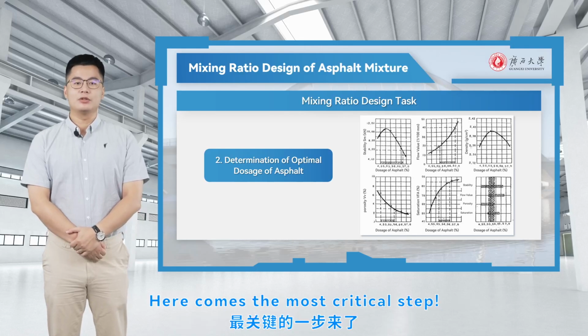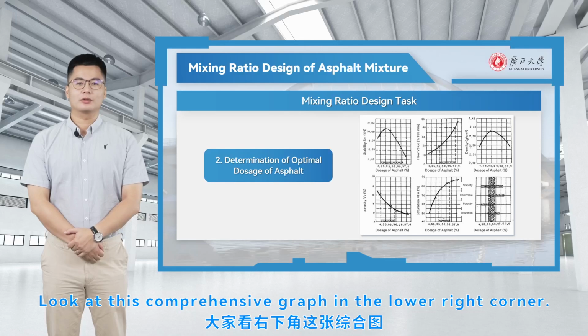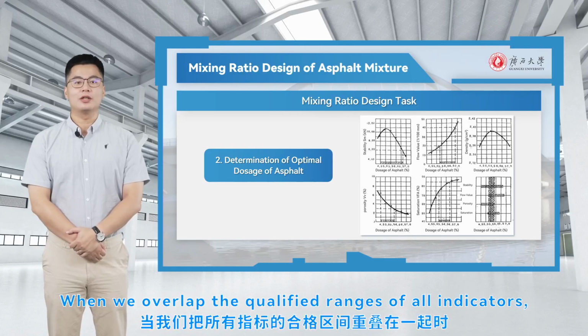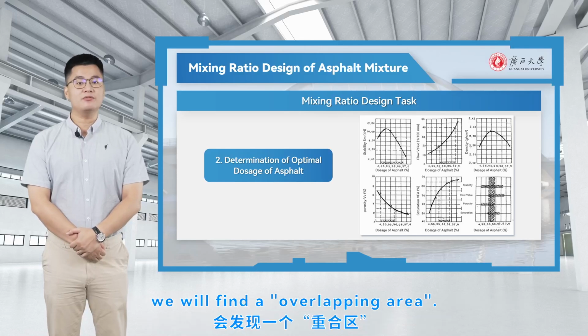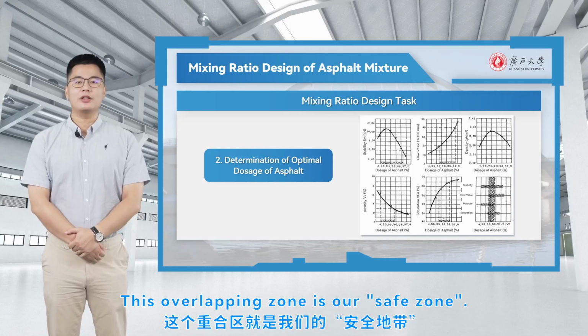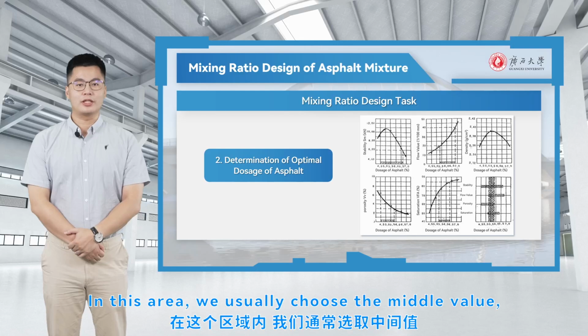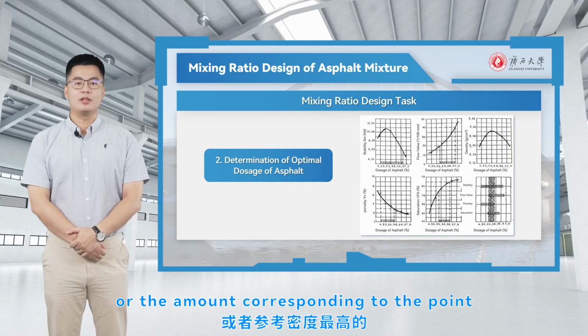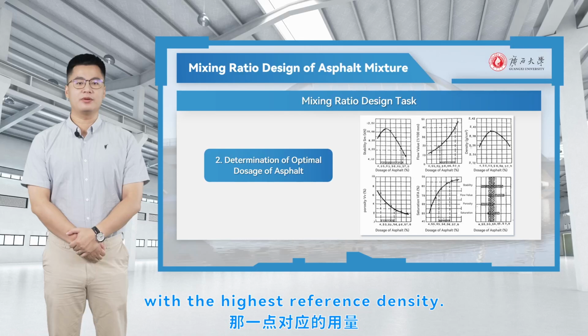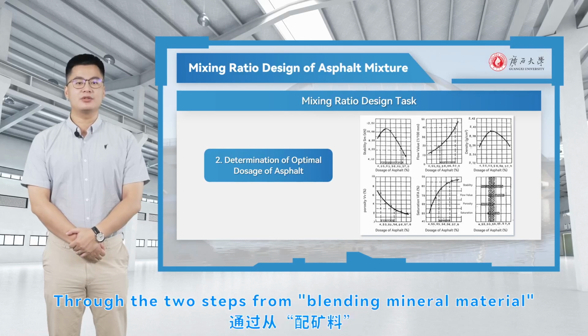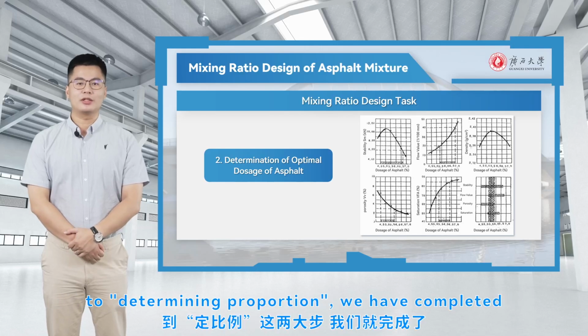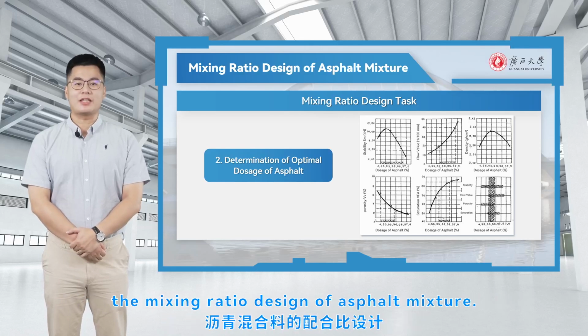Here comes the most critical step. Look at this comprehensive graph in the lower right corner. When we overlap the qualified ranges of all indicators, we will find an overlapping area. This overlapping zone is our safe zone. In this area, we usually choose the middle value or the amount corresponding to the point with the highest reference density. Through the two steps from blending mineral material to determining proportion, we have completed the mixing ratio design of asphalt mixture.